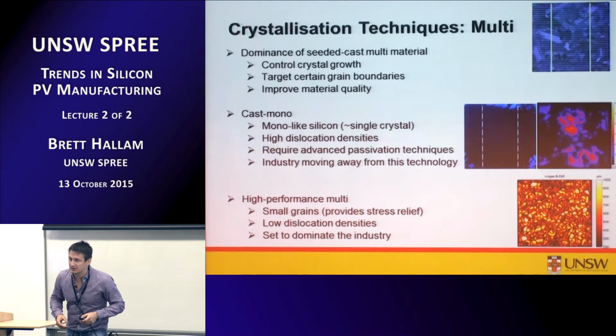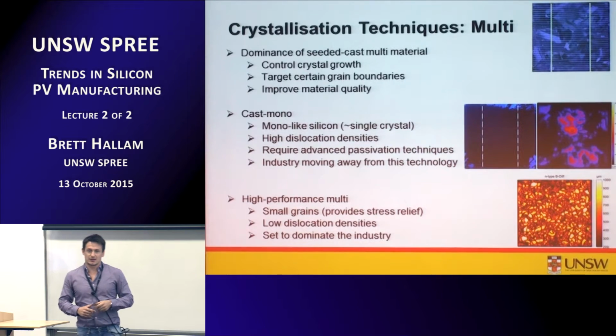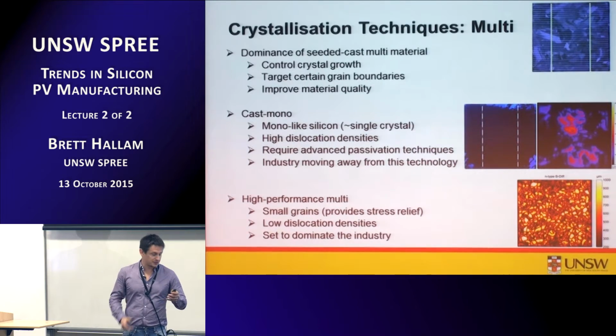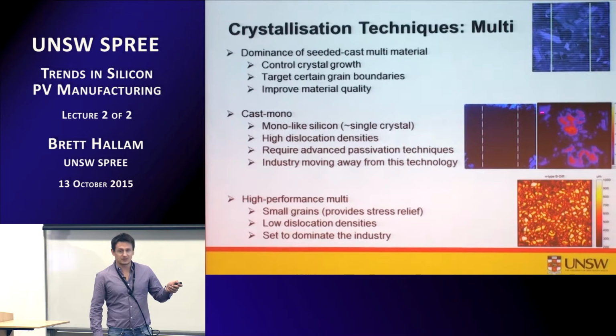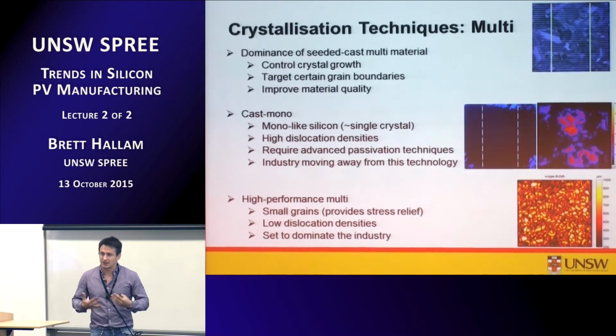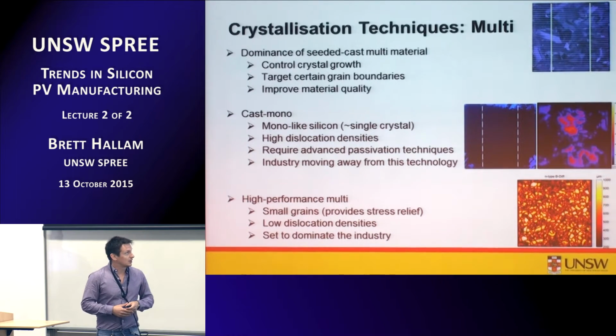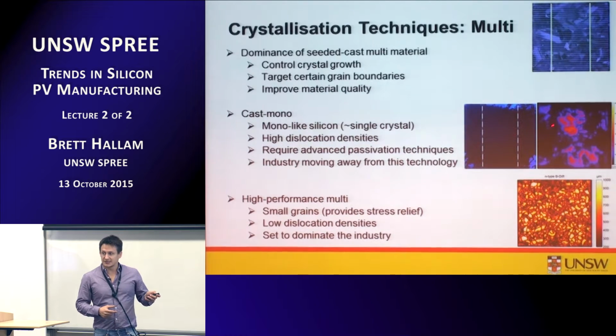Exactly. Yeah, so that's one advantage of this technology. Potentially, and BP developed this technology a few years ago. They had patents on it, their cast mono process, that they can grow single crystalline silicon but potentially avoid LID, lower oxygen concentrations, and therefore lower boron oxygen.